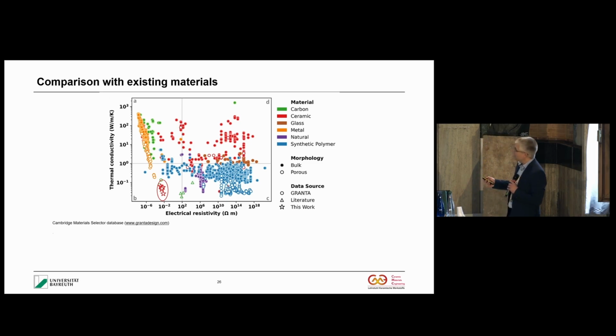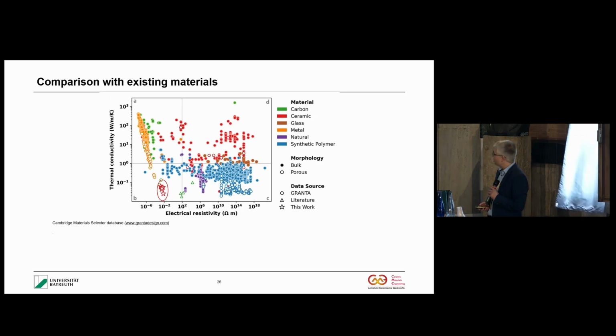And if you use an Ashby diagram and a database, you find out that the material is very unique because you have a low electrical resistivity, but the thermal conductivity is also quite low, which is quite unique. And usually the electrical and the thermal conductivity are coupled, but in this kind of material they are actually decoupled.